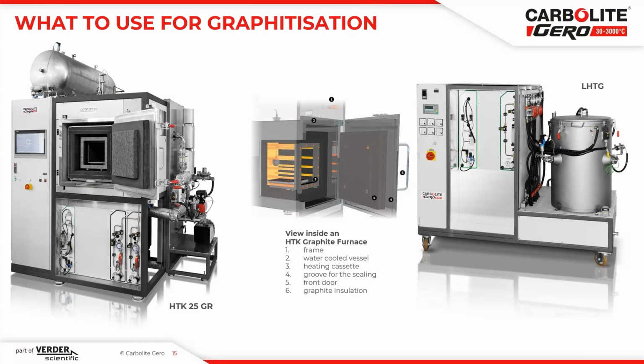For graphitization, on the other hand, we've got a much more high-end precision system. As Fabian said, we've gone through most of the late production phase. The off-gases are residual; they're not too much of a heavy duty for the furnace. They feature graphite felt insulation, and they've got graphite heating elements. These systems will go up to 3,000 degrees centigrade, and that's measured using optical pyrometers. We use a combination of thermocouple control at lower temperatures and optical pyrometers to give us the best temperature accuracy through the process flow. We also incorporate an afterburner system to deal effectively with the off-gases, and you can see that on the right-hand side of the first unit here.